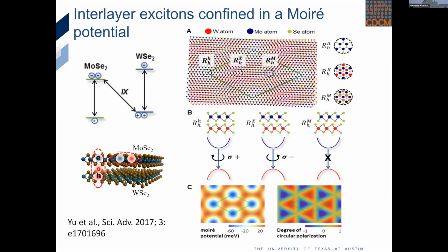The selection rule also becomes much more complicated, as articulated in this first paper by Yao Wang. If you were able to put excitons in a spatially resolved manner, if I only keep track of the K valley, and there will always be a time reversal copy in the K prime valley, at 2 of the high symmetry stacking points you'd actually have sigma plus, sigma minus alternating selection rules. And then at the third point, you actually have a dipole moment that's perpendicular to the plane.